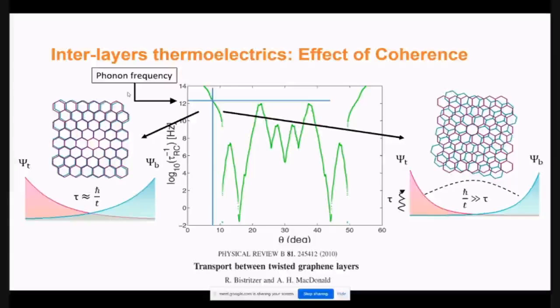Yeah. So again, let me tell Saurabh, you are asking questions which are happening now, but I'll try to give you the answer. See, it turns out that below 5 to 6 degrees here, the two layers are starting to talk to each other by hopping electrons from one layer to the other. But the hybridization is still not completely leading to reconstruction of the Dirac bands. It turns out that a significant amount of reconstruction or modification happens in a small regime, when the other effect starts coming in, which is around 1.5 degrees or something of that sort.